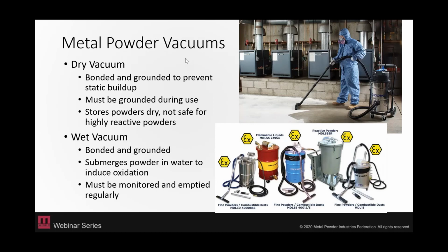Dry vacuums are bonded and grounded to prevent that static buildup, and they must be grounded during use. That's not just plugging it into the wall. There's actually a separate grounding strap that gets plugged into your grounding column in your building. And these store the powders dry, so you just can't use dry vacuums for certain reactive powders. When you have reactive powders, you have to use what's called a wet vacuum.